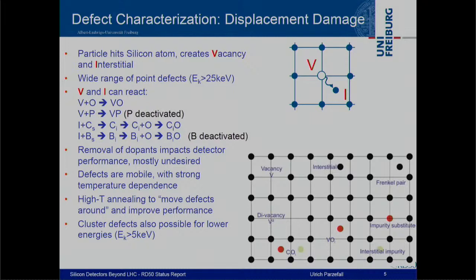Then these defects can react. For example, a vacancy and an oxygen can form a cluster, a vacancy and phosphorus can form a cluster, which would then deactivate your dopant. The same can happen in slightly more complex ways when you have interstitials and carbon reacting: the carbon at a lattice site could then become an interstitial, and in the end you get a carbon-oxygen cluster. Something very similar can happen for boron.